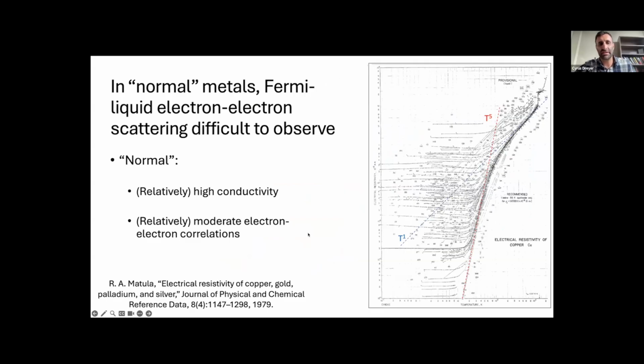By normal metals, I mean metals with relatively high conductivity and therefore relatively moderate to low electron correlations. Here's an example of a bunch of measurements done on copper, and you can very clearly see the Bloch-Gruneisen electron-phonon behavior, T to the fifth turning into T linear. But it's very hard to resolve any kind of Fermi-liquid T squared regime at low temperatures because of the complications from residual resistivity and from the dominance of phonons.